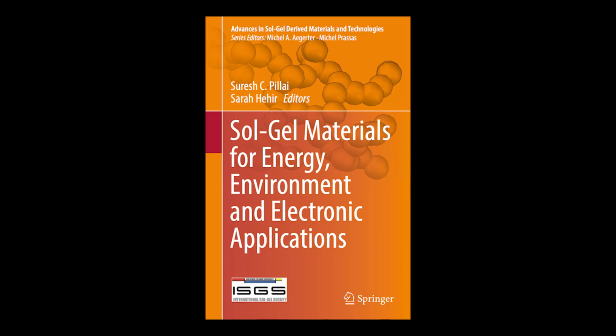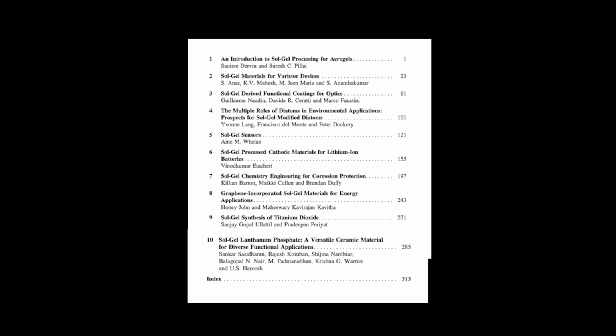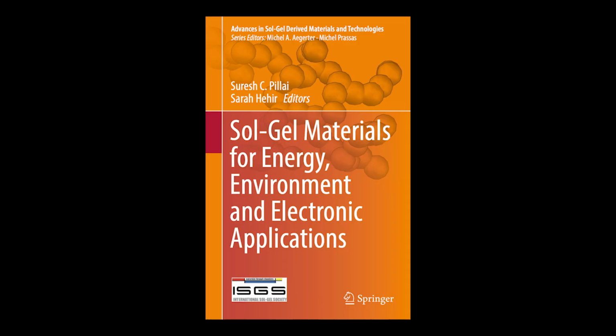The most surprising application mentioned in the chapter, however, relates to its interaction, or lack thereof, with molten metals. Yes, this is perhaps its most specialized and unique utility. LaPO4 demonstrates remarkable non-reactivity and non-wettability with many molten metals, particularly non-ferrous ones. The chapter describes tests where sintered disks of LaPO4 were exposed to molten metallic silver. The silver exhibited a contact angle greater than 125 degrees on the ceramic surface.